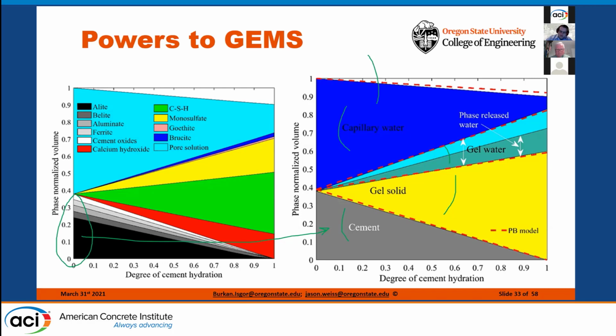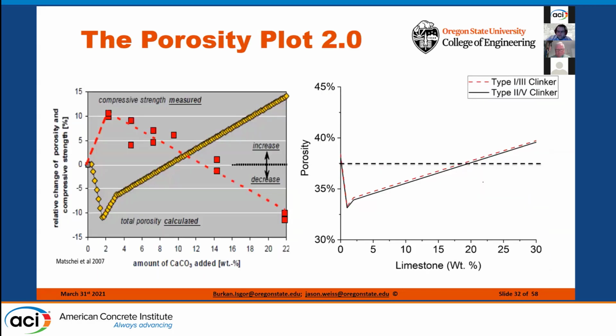So the cement is relatively easy. The capillary water is relatively easy. For gel water, we do some accounting to figure out which of these phases give up water, and then we take a portion of the remaining water and we put that into the system, and we have a system that correlates really well. So the orange lines here are the prediction through GEMS using something we call a pore partitioning model. The color in the background is Powers' model, and there's a very strong correlation between the two.